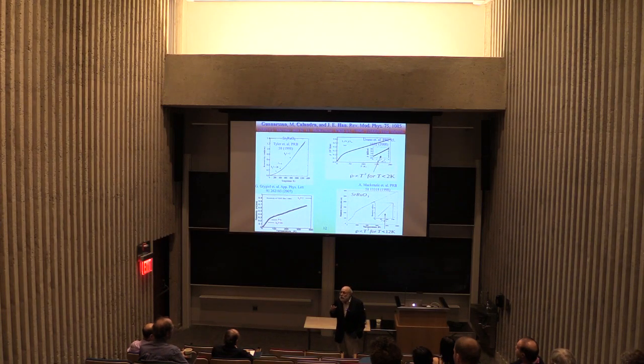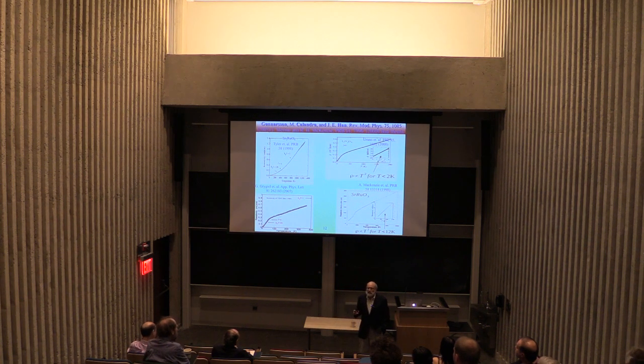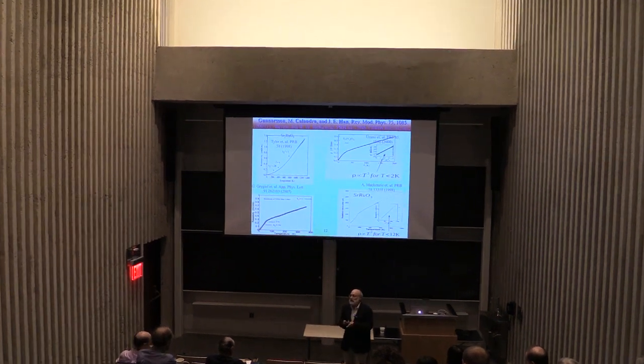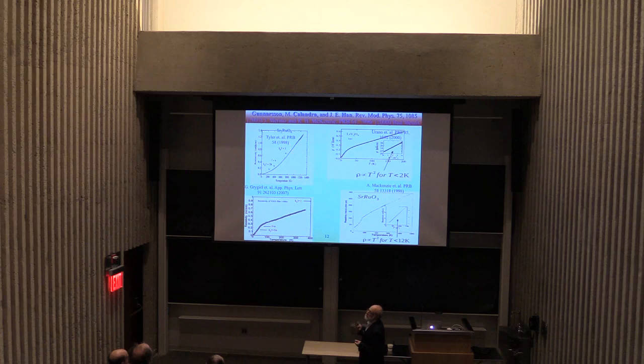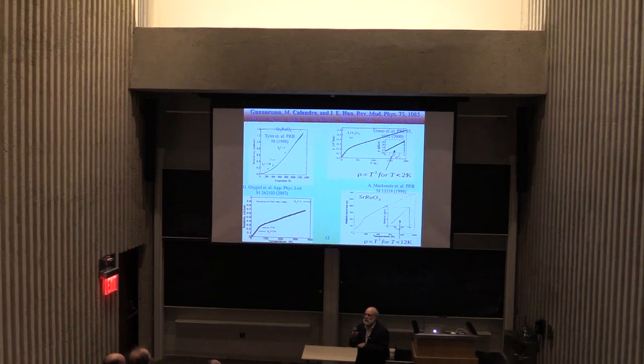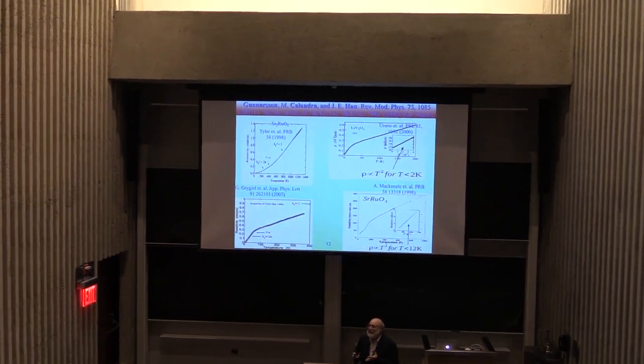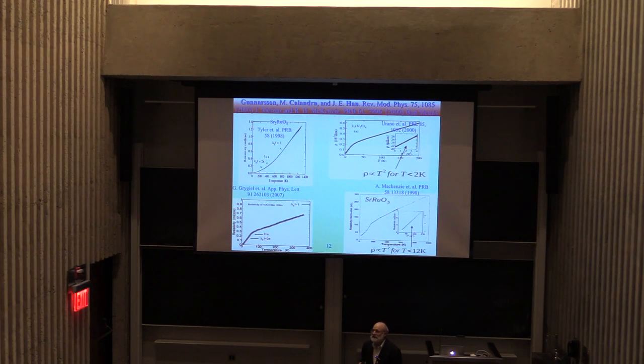And let me explain qualitatively why this is so puzzling. The point is that the standard model is based on thinking of the electron as a wave in the solid. A wave has some wavelength. And then every now and then the wave gets scattered by some defect or by some collision effect and acquires a mean free path. Now, this picture makes sense when the mean free path is much longer than the wavelength. To get this very high resistance, the mean free path has to be smaller than the wavelength. And that doesn't make internal sense in terms of the model.